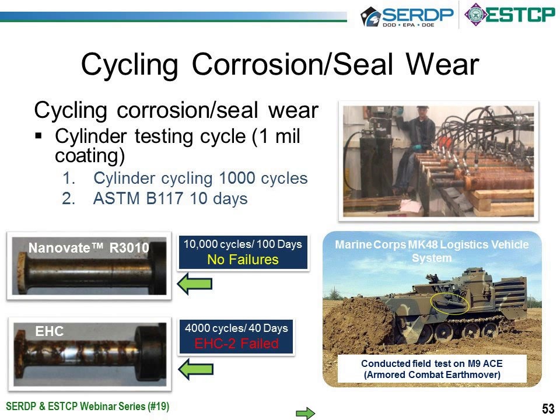A question was asked earlier about the benefits of this coating system, and we saw that firsthand with some testing that we did with NAVC. These are basically hydraulic cylinders that have been actuated in a corrosive environment. The illustration up top is their actual testing apparatus. These cylinders are cycled 1,000 times. They are then moved into a corrosive environment, which is an artificial salt fog chamber, for 10 days, and then returned to another 1,000 cycles.